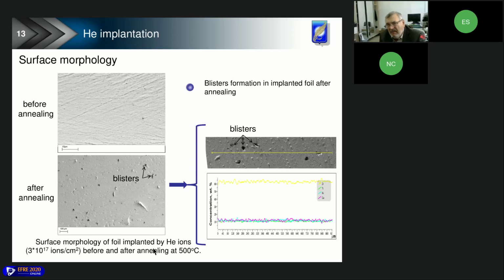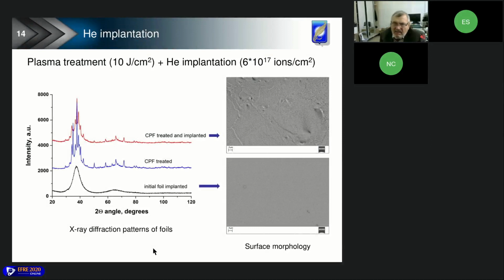Well, helium implantation was also carried out into samples which were previously subjected to plasma treatment. The dose was increased 2 times to enhance implantation effects. In this figure you can see the diffraction pattern of the foil treated by plasma flow and the diffraction pattern of the foil treated by plasma flow and implanted by helium ions. In general, there are no significant changes between these two patterns. Some difference in intensity of the diffraction lines was simply caused by the orientation of the foil to the X-rays during analysis. I mean that no sample rotation was used during X-ray diffraction investigation.